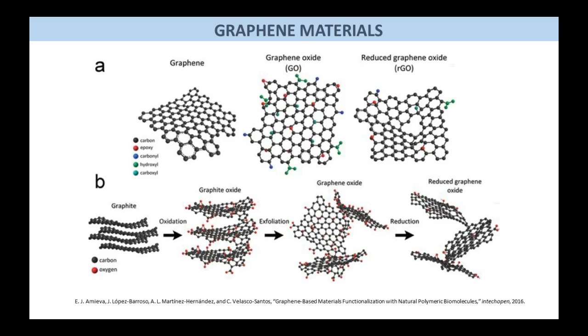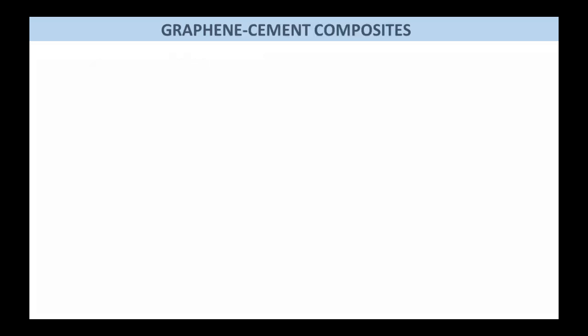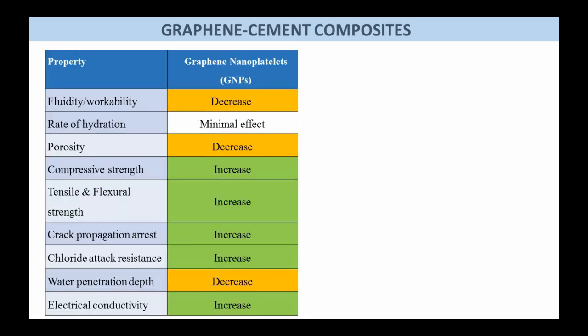And unfortunately in the literature it's not always clear what type of graphene is used, how many layers it has, and all these properties actually affect the resultant properties of the composite at the end. And in terms of graphene cement composites, I'm using a multi-layer form of graphene, so not the very thin one-layer graphene, because that would be prohibitively expensive for anything in concrete. But I'm using something called graphene nanoplatelets, which have about 40 nanometers thickness.